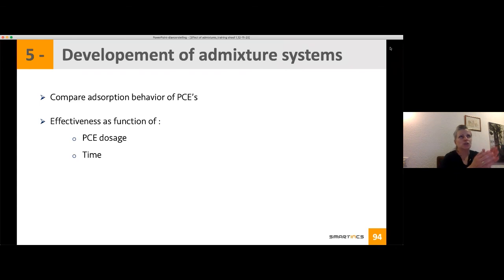And you can also check in that sense the effect with a time of addition. I haven't mentioned it yet, but if you put your admixture right away, or if you put part of your admixture immediately, and then you have a delayed addition, so a few seconds later, you add the rest of your admixture, you will get also different properties. And this has to do with the initial hydration and initial reaction that take place in the first minute of your mix.